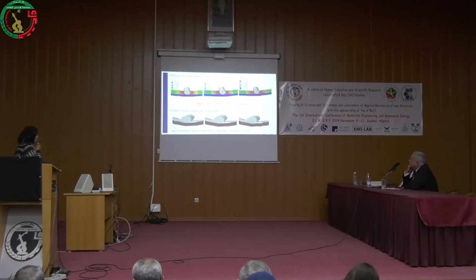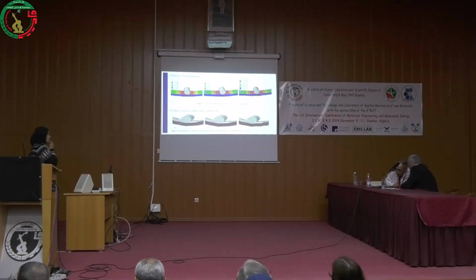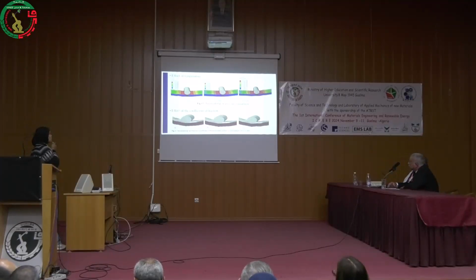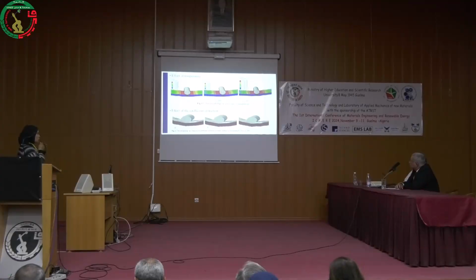For the effect of temperature, we can see that as the temperature changes from 25 degrees Celsius to 215 degrees Celsius, the von Mises stress is decreasing from 302 megapascal to 295 megapascal. But for the friction influence, no huge results are obtained. In other words, for the friction, no change in the morphological behavior is noticed.